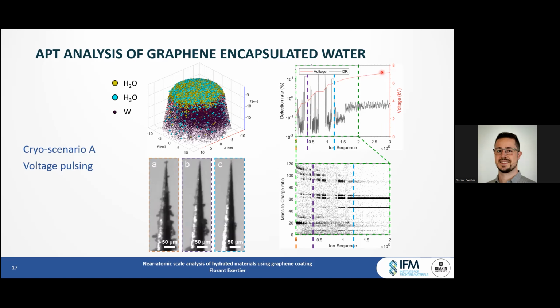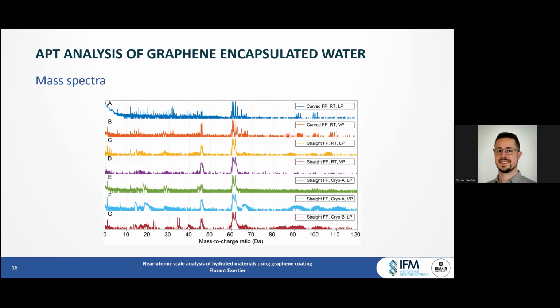And here we have several optical images that were taken in situ of the atom probe, and that corresponds each to the vertical lines in orange, purple, and blue. And we can clearly see that there was a bit of frost building up at the tip, but that it was clearly removed. And after that, we were still obtaining some strong water signal. So now let's have a look at the mass spectra. So the main point is the peaks corresponding to graphene, so with carbon, for instance, and to water that were detected in almost each data set.